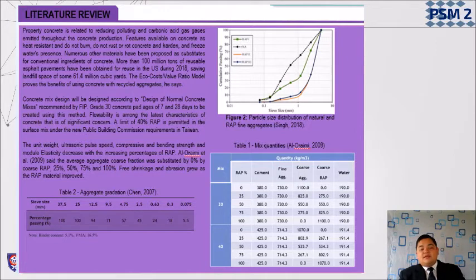The unit weight, ultrasonic pulse, compressive and bending strength, and modulus of elasticity decrease with increasing percentage of RAP, which means that when the researchers add more percentage of RAP aggregates in the concrete mixture, the strength of the concrete will decrease. This is because maybe the admixture from the RAP itself affects the concrete characteristics.